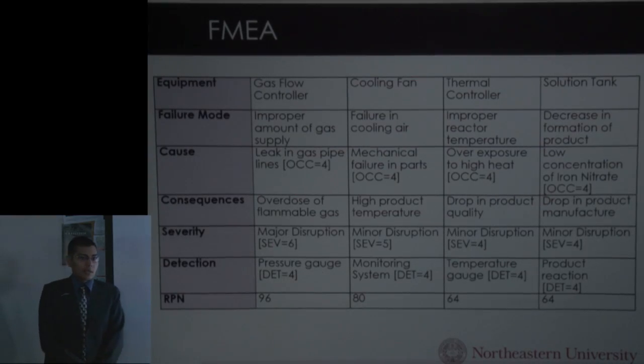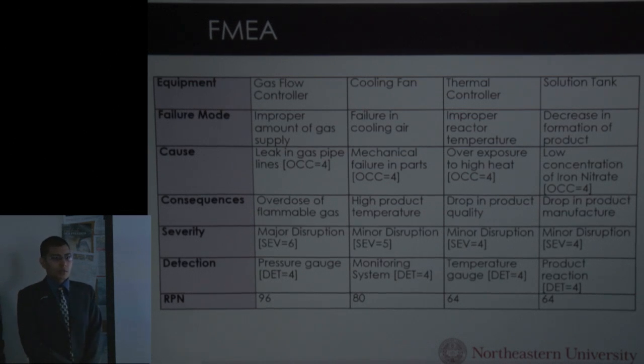So here is our FMEA result. Based on our process, we discovered 4 key places where if the equipment goes wrong, then our process gets hampered. The first one is the gas flow controller. It's responsible for regulating the right concentration of gas into the tube furnace. In case it malfunctions due to certain leakage of gas, then the concentration of gas going into the system decreases, which hampers our reaction rate and ultimately decreases our product quality.